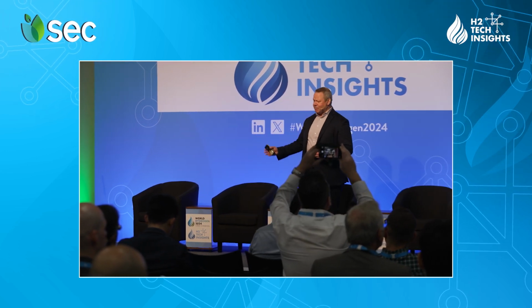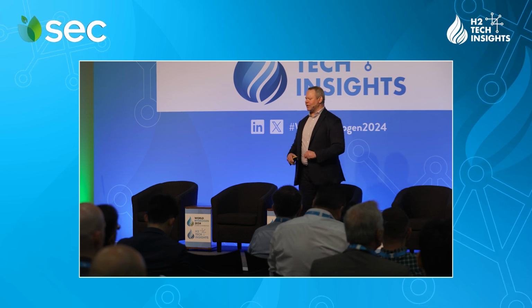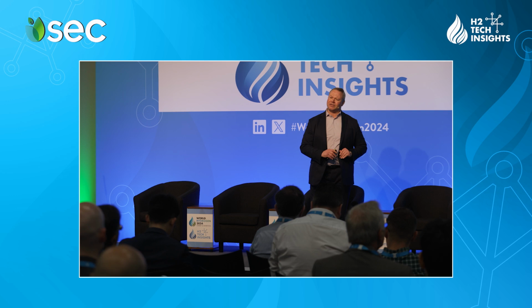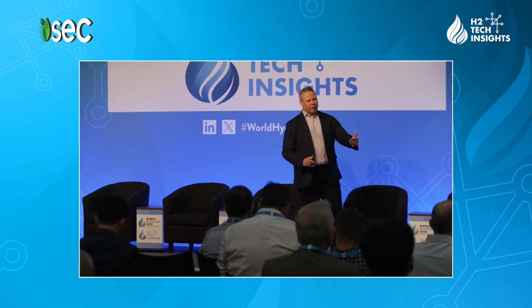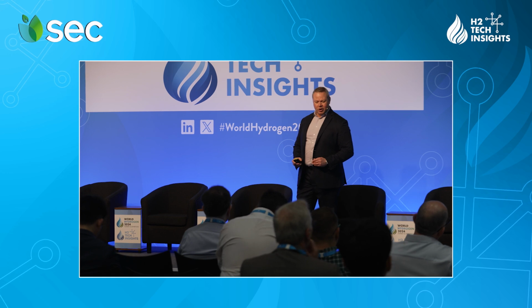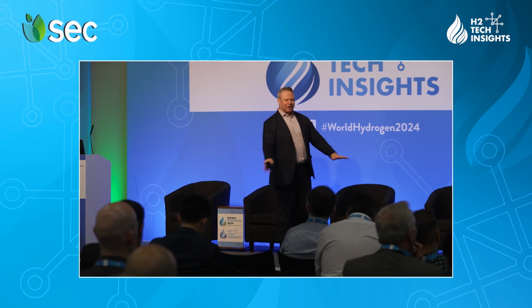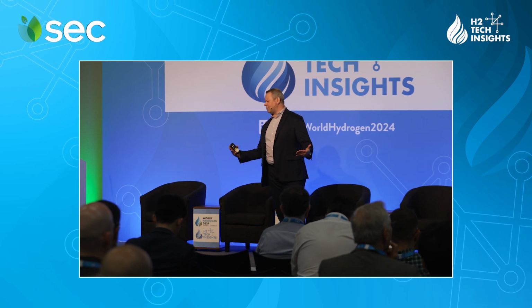Compared to our next-gen PTL, which is exceedingly smooth and perfect. We use smaller particles, the pores are smaller, the pore size distribution is tighter. And then, even at this 0.1 milligrams per centimeter squared, with our next-gen material, we're again able to reap even greater benefits from this next-gen approach. And this is entirely morphological. Everything else is the same in the cell. This is just by changing the surface structure of the PTL.